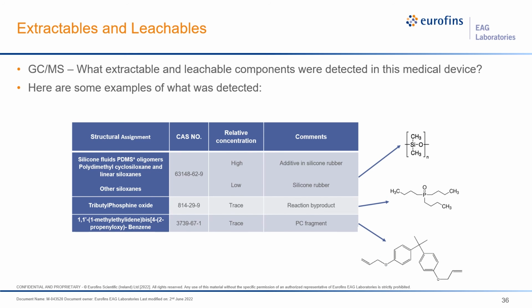We did detect some other unique components aside from the siloxane-related species. One of them was tributylphosphine oxide. This was detected at a trace level and is a common reaction byproduct that can be associated with the catalysis of this material. We also detected a polycarbonate fragment. So if you see that structure down the bottom right, if you have some chemical intuition and you remember our structures from the first case study, it should look pretty familiar. So that's a BPA fragment.